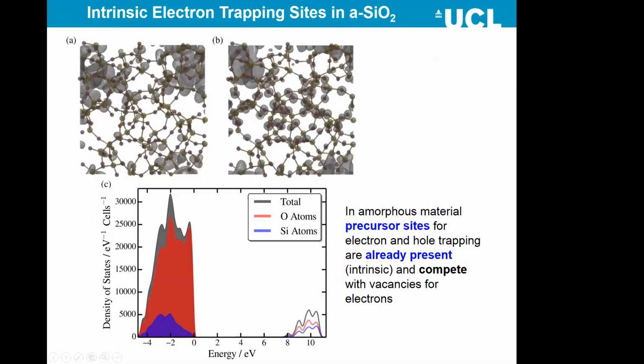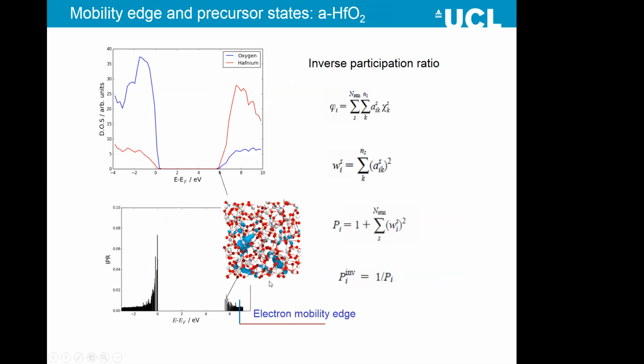So what we observe is that, when we produce such a system, for example amorphous silica, and we put some electrons in or holes, we see some states which are partially localized, in a similar way as Jochen again was showing. So you have some partial localization. And then if we allow the system to relax, electrons or holes may localize.